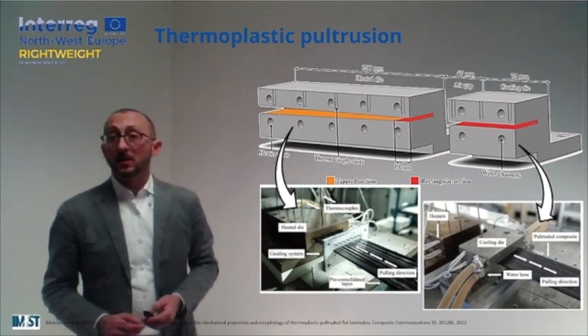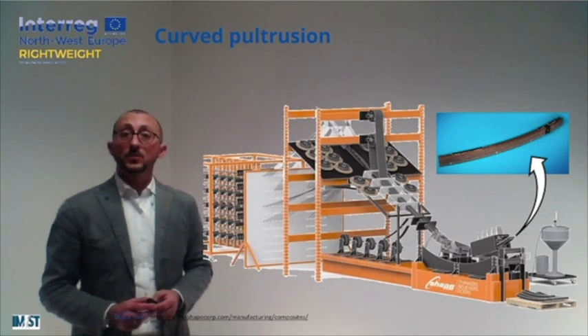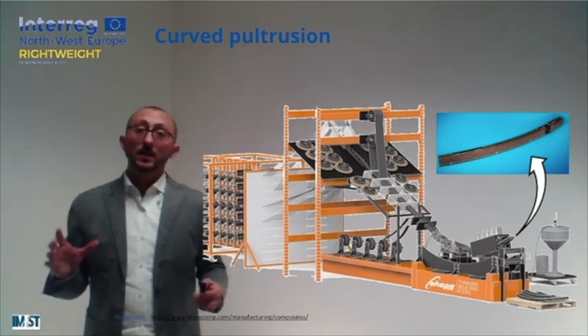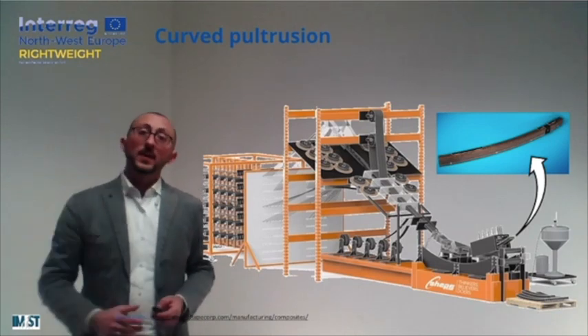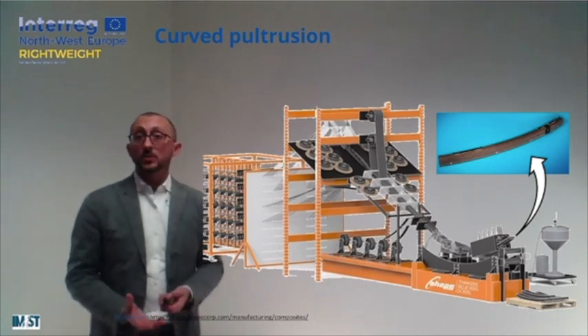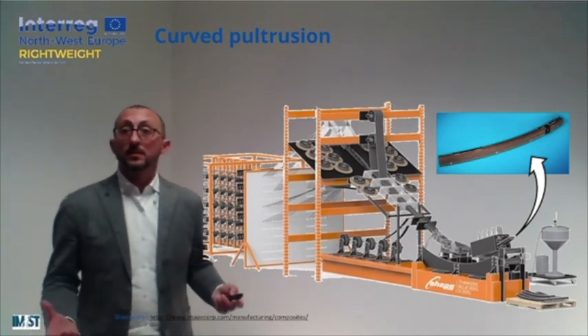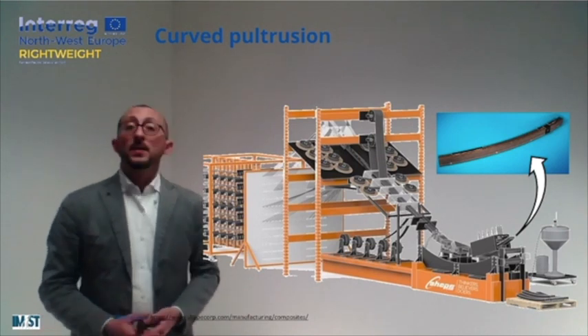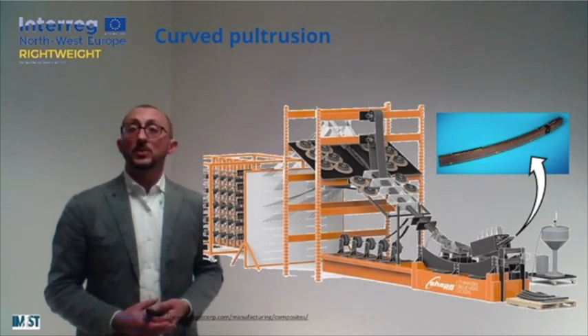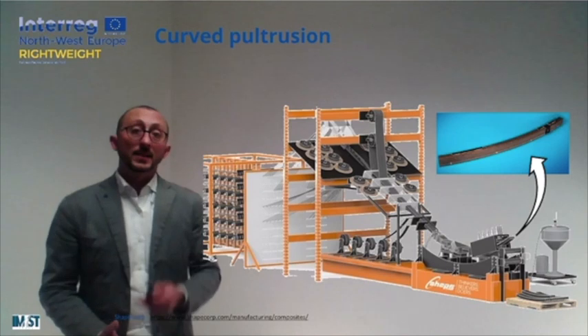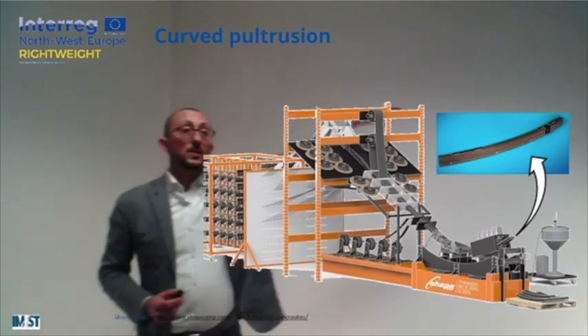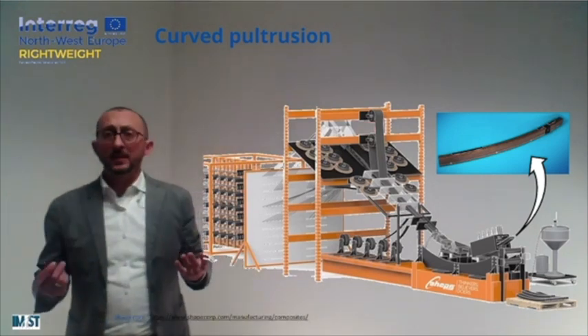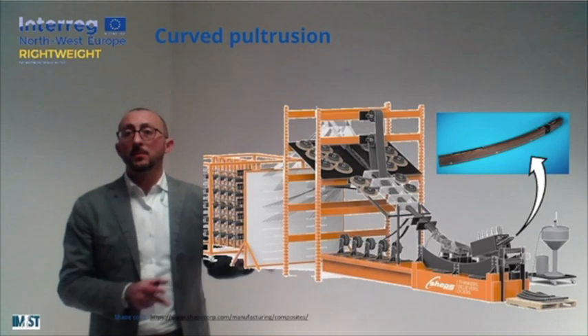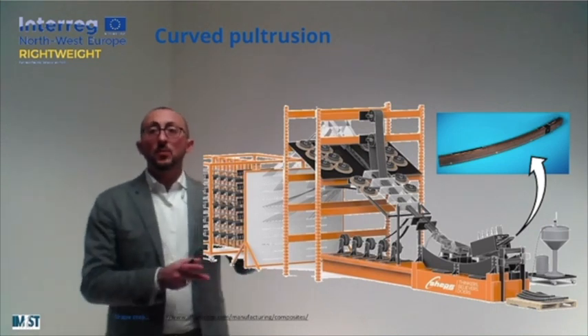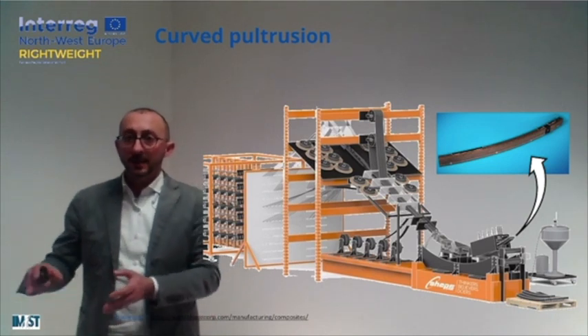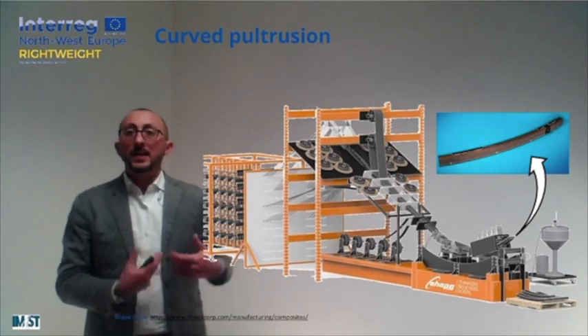Other interesting variants of the pultrusion line are given by the so-called curved pultrusion. In general, when we think about pultrusion, we are thinking about a rectilinear profile with constant cross-section, so a strong limitation for the components and structures that we can realize. So recent developments of the pultrusion machine enable us also to realize some kind of curved component, as you can see over there, using quite a different approach based on the usage of a moving, oscillating die that is actually moved back and forth in order to take more material inside and then move back, heating and curing the material.